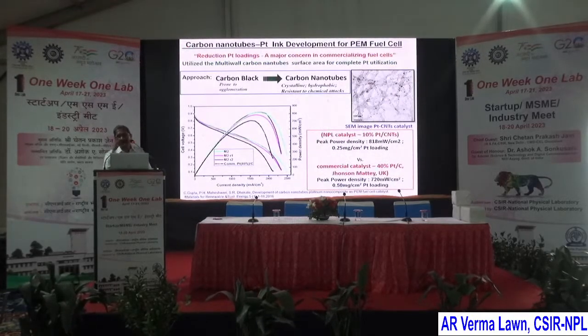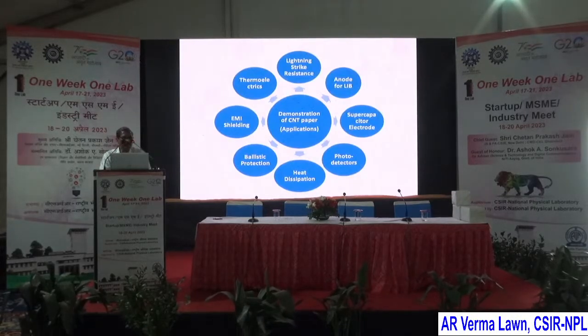One application of the carbon nanotube is to use it as a catalyst support. I have told you that in the hydrogen-based fuel cell, the catalyst plays a very important role in the dissociation of hydrogen into ions and electrons. So we have to use a platinum catalyst, but one day we may not have platinum. So how can we reduce the quantity of platinum catalyst in the fuel cell application? We have to use a high surface area material. Carbon nanotubes have very high surface area, and we can deposit the platinum catalyst on them. Then we are able to reduce the catalyst in the hydrogen fuel cell by 50%. This is one example of the application of carbon nanotube as a catalyst support for the polymer electrolyte membrane fuel cell.